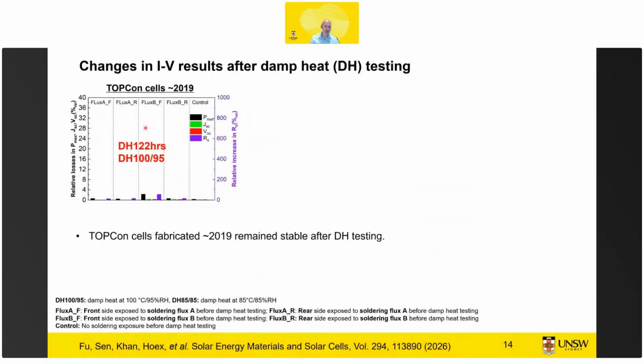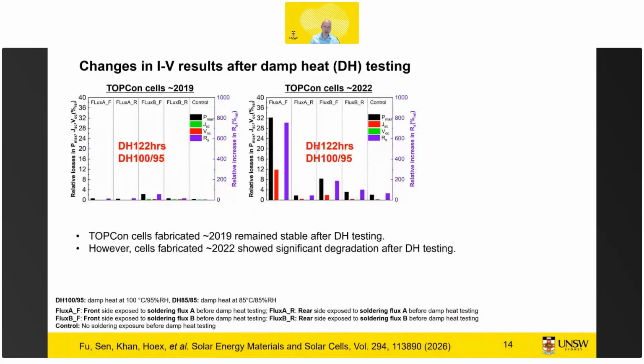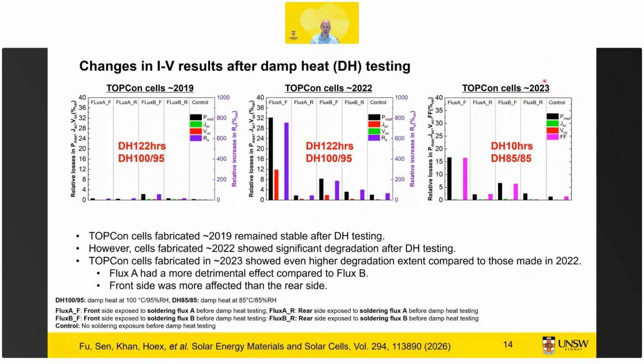So if we then look at the cells from 2019, we see that this axis is performance losses. We actually see that both soldering fluxes are not really able to corrode the cells. So we see even after 122 hours, not really a change in performance. The cells from 2022 were a lot more sensitive, and this is what we've seen consistently in our testing, that the more mature TOPCon became, the more sensitive it became to corrosion before the introduction of laser-assisted firing. So it was a lot worse, but still not as bad as the cells we tested from 2023, where the